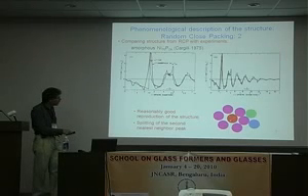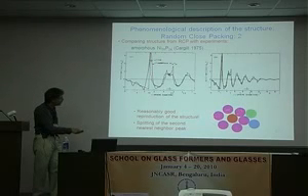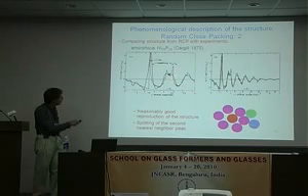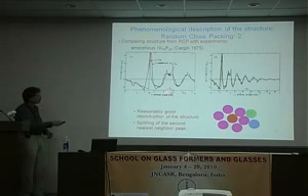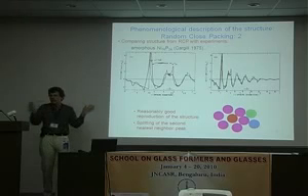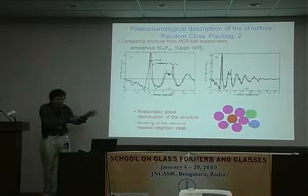If the red particle is sitting here at the origin, this first peak here are the pink particles, so that's the first nearest neighbor shell. And then the second nearest neighbor shell, grossly speaking, has two configurations. You have the red-green one, which is a distance slightly smaller than red-blue. More or less both of them are in the second nearest neighbor shell. That's why it's split. So there's no magic. Some people made a lot of fuss: well, glassiness has something to do with splitting of the second nearest peak. Nothing. It's just local packing arrangement.